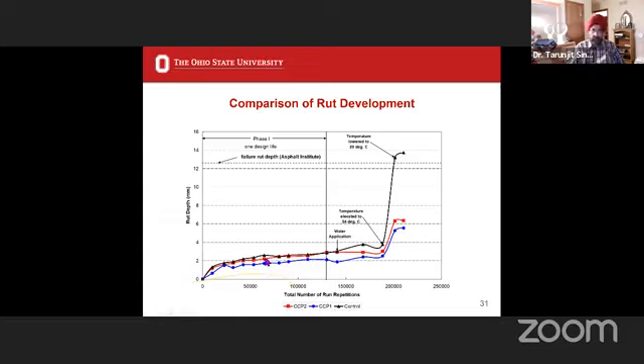You can see that one of the CCP sections behaved quite similarly up till 20 years of highway traffic. The one CCP section behaved slightly better. But then water was applied. The time when rutting really began to happen is when the temperature of the facility was increased. And now you can see, look at this line. This is the failure depth, rutting depth for asphalt, in terms of millimeters. Our asphalt pavement control section failed, not structurally, but in performance, whereas the CCP sections did not.